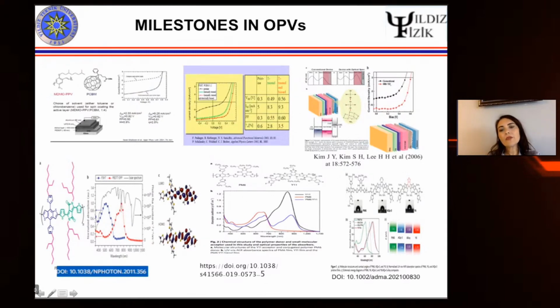Later on, in Heeger's group, by putting some kind of optical spacers in the inverted geometry, they also got 5% efficiency. And over the years, non-fullerene materials and also low band gap polymers instead of P3HT, which are more suitable for photon harvesting, were used. Then the fullerene derivatives were replaced by different kinds of non-fullerene derivatives, and the efficiencies reached up to 18%.